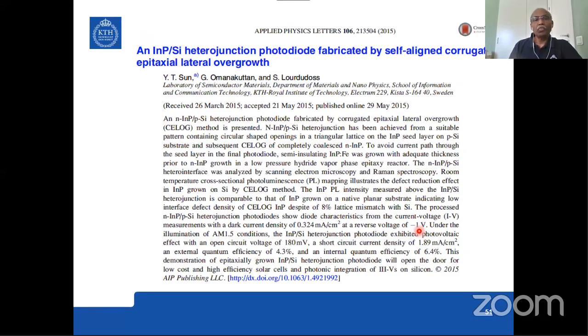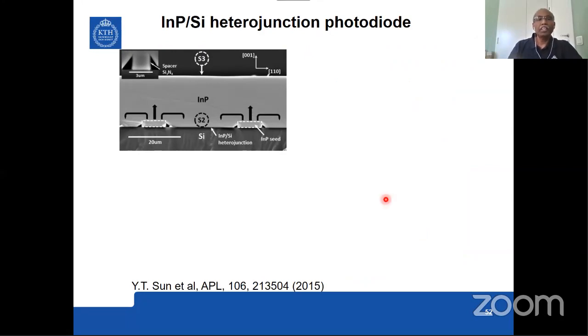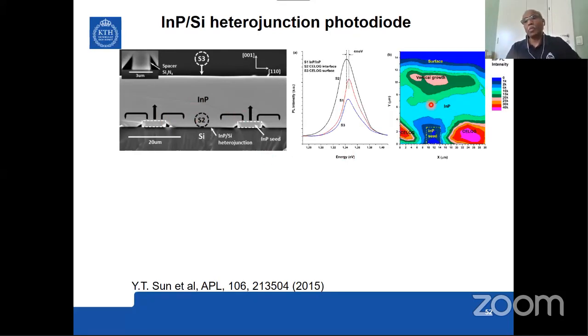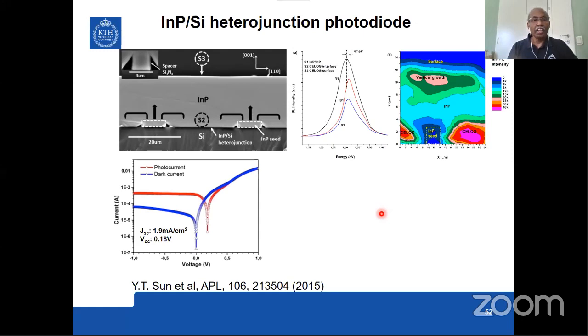And so we wanted to demonstrate whether this works even as a PN diode. And we made this kind of structure. We allowed it to coalesce. And then you see here, this is the PL mapping of this structure. This is a seed, and the CELOG layer, what we call CELOG layer here, which is in connection with the silicon at the interface. It is the best quality. The intensity is the highest here. And of course, it is very mediocre results, but this is a proof of concept. At least we can show that the diode works. This is the photocurrent, and here is the dark current, even though the short circuit current density and the open circuit voltage are not really fantastic. But still, it is a proof of concept that these things work.